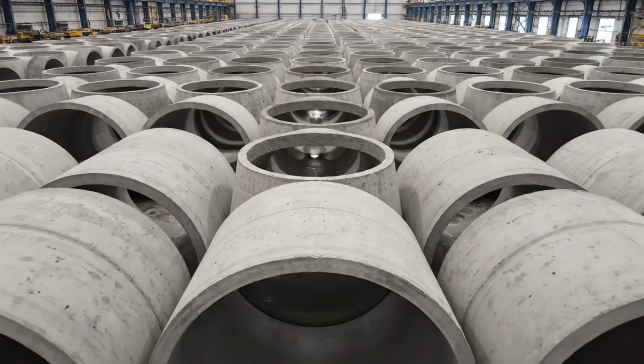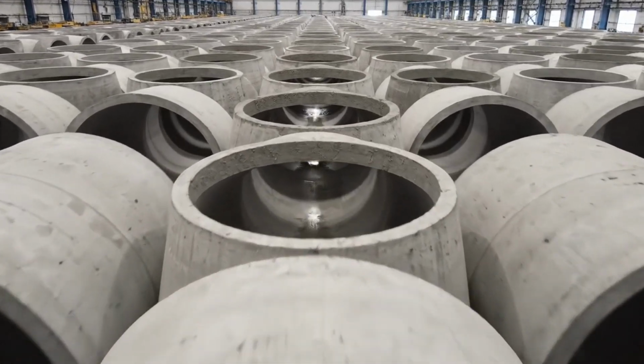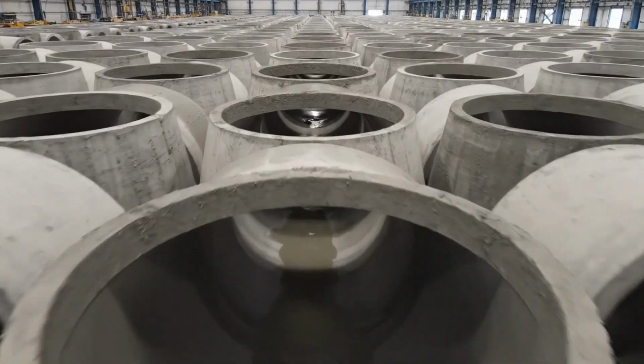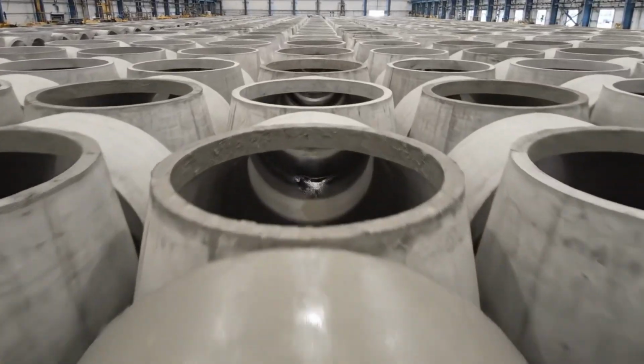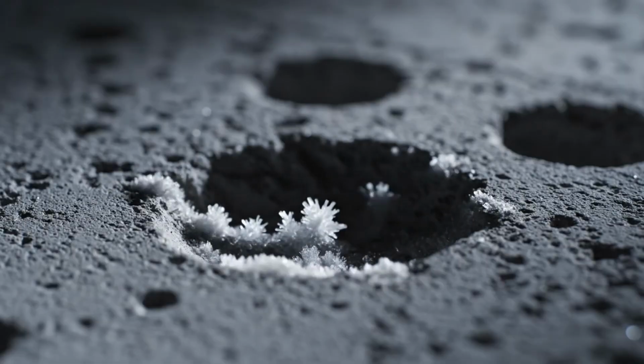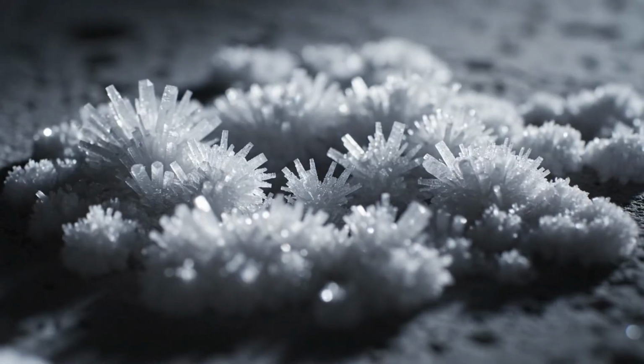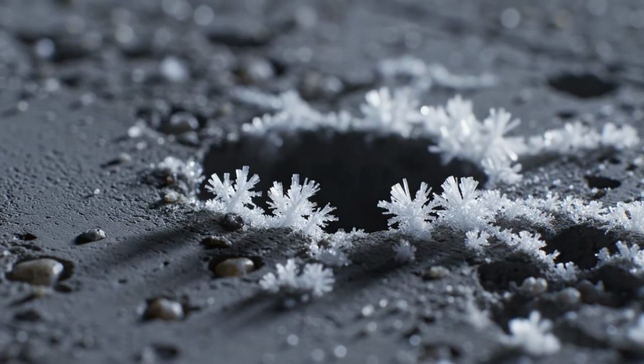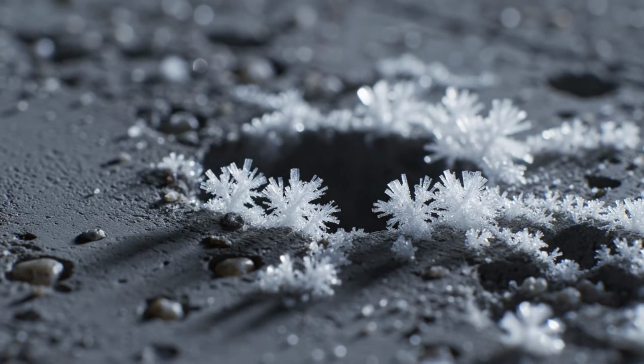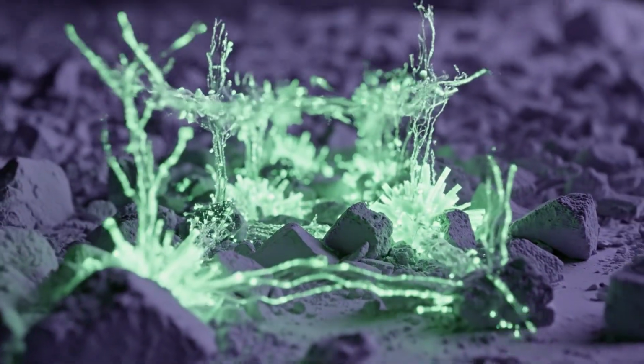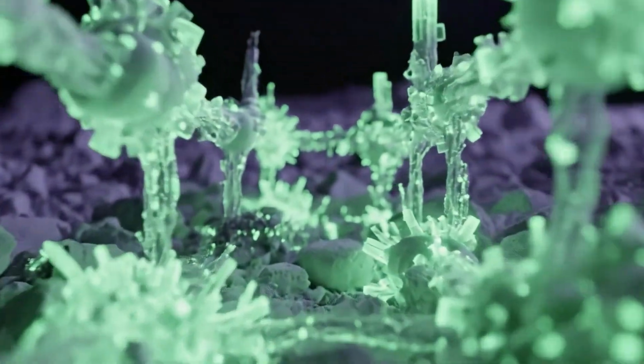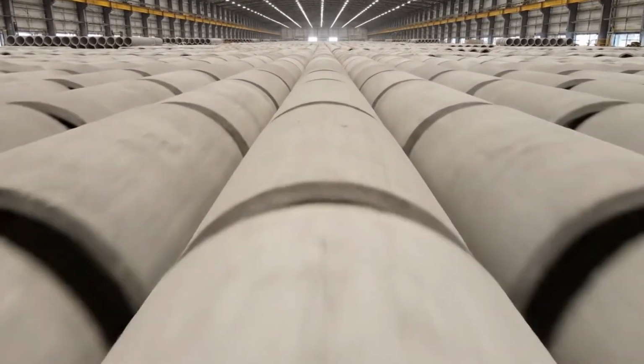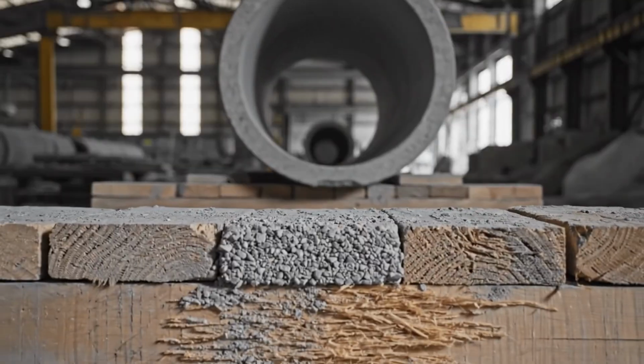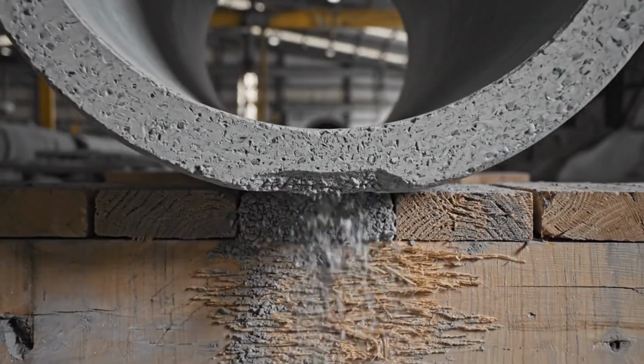Humidity plays a central role. If concrete loses water too quickly, cement hydration is interrupted prematurely, and shrinkage microcracks can appear. These cracks, although small, open the way to future problems: lower durability, higher permeability, and worse behavior against chemical agents in the soil or transported water. Therefore, many plants apply wet curing, misting, or storage in environments where humidity is conserved during the first critical days.